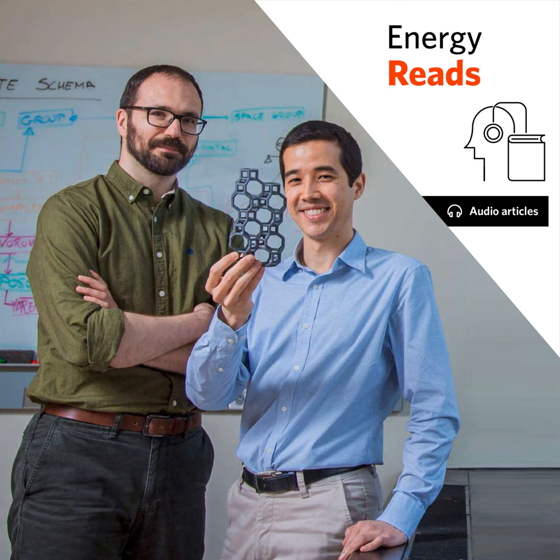Experiments using that in-between templating molecule resulted in the formation of not one zeolite or the other, but a combination of the two in a single solid. The result blends two different structures together in a way that the final result is better than the sum of its parts, says Schwalbe-Coda. The catalyst is like the one used in catalytic converters in today's trucks, only better.